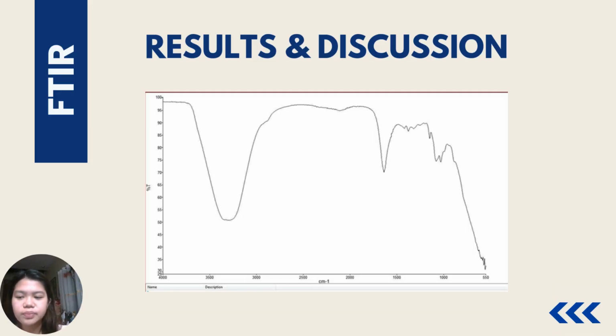In this study, the FTIR spectrum of the chitosan sample confirms its structural composition through characteristic absorption bands. The broad band at 3,200 to 3,500 per centimeter indicates O-H and N-H stretching, highlighting the presence of hydroxyl and amine groups, which contribute to chitosan's hydrophilicity. A distinct peak at approximately 1,650 per centimeter corresponds to C=O stretching of amide I, signifying residual acetyl groups from partial deacetylation, while the peak around 1,550 per centimeter is attributed to N-H.